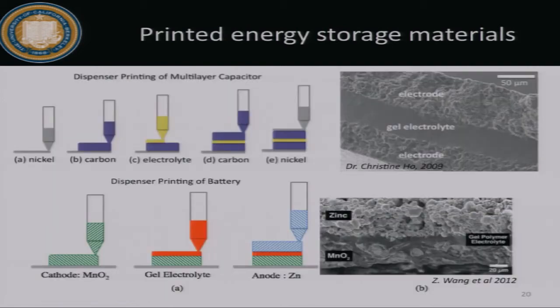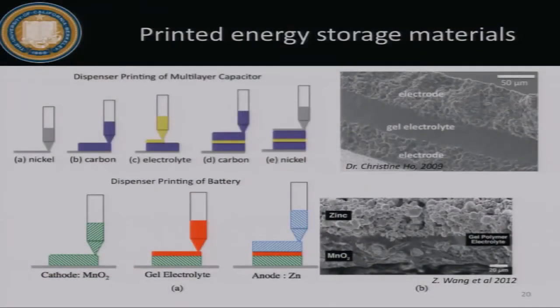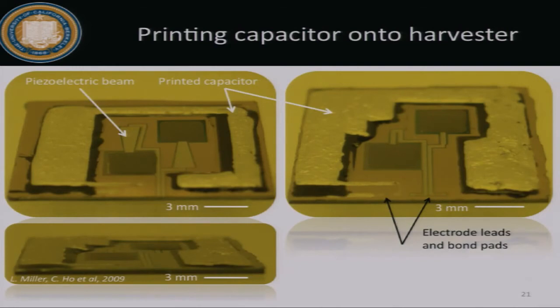So this is showing how it works when you print a battery or capacitor. This is the work of Christine Ho and Joe Wang. And you can print layer by layer, just letting the layers dry in between. So like for Christine's multi-layer capacitor here, it was a nickel current collector, a carbon electrode, and then another carbon layer, and a top nickel current collector. So the silver you see is that nickel current collector.